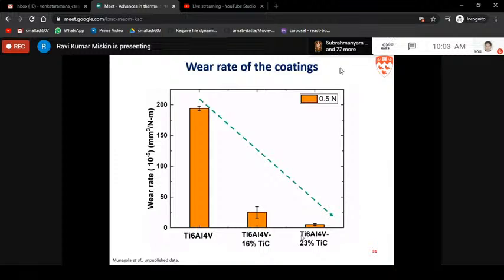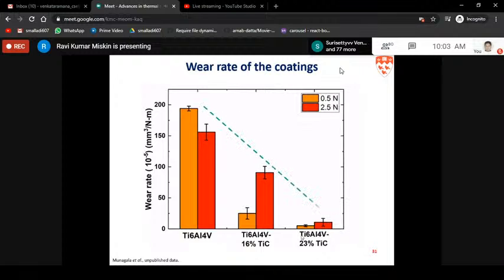So we are technically saving our material, improving its wear, and also getting low friction. Even at 2.5 Newton normal load, our 23% titanium carbide TiC was the best performing coating, which gave an extremely low wear rate. When you compare with our base coating, that is titanium 64 itself, your composite wore almost 10 times less. So that's the advantage of incorporating titanium carbide particles into the matrix itself. Next slide.